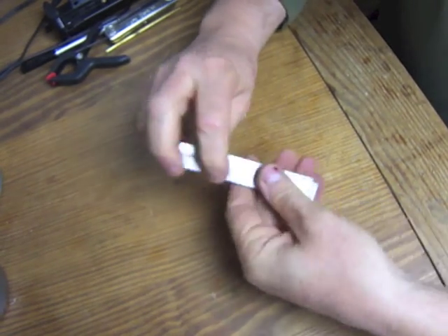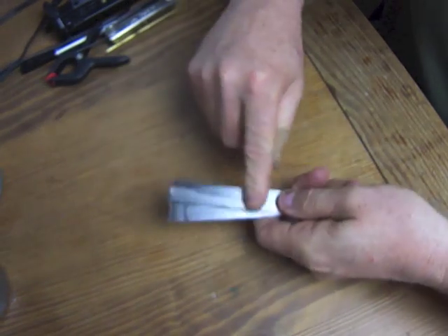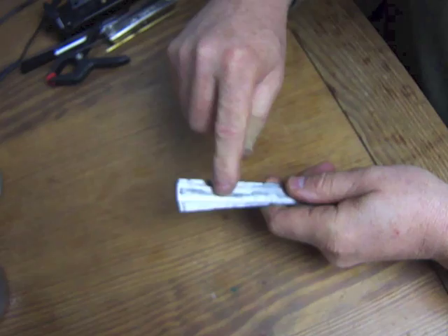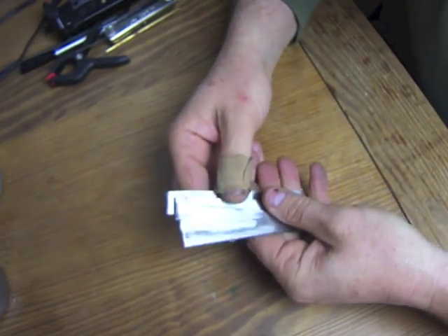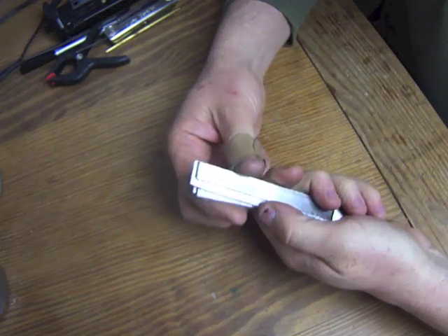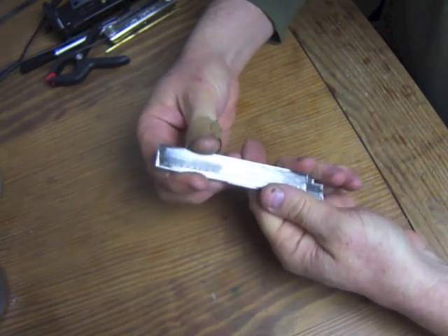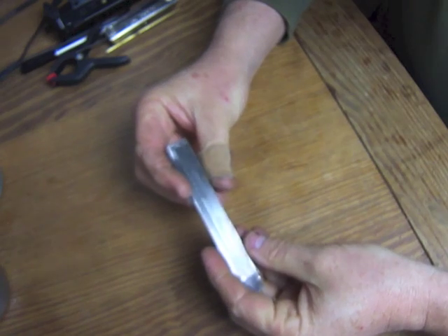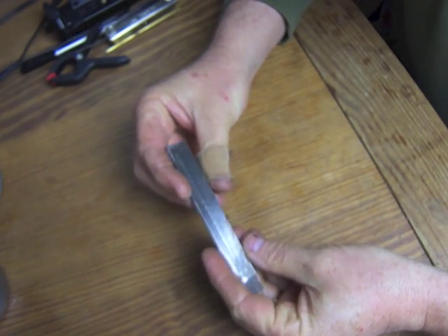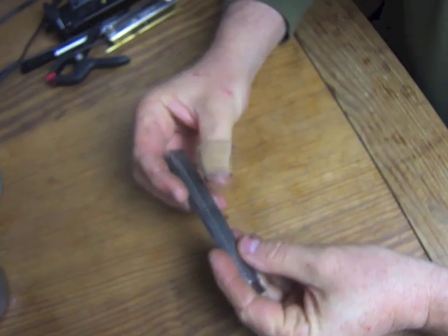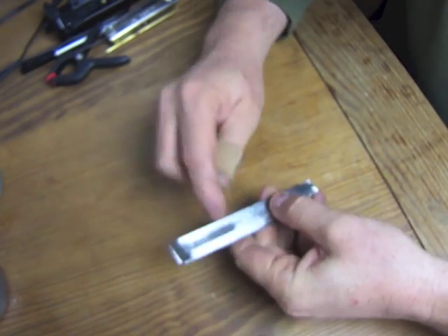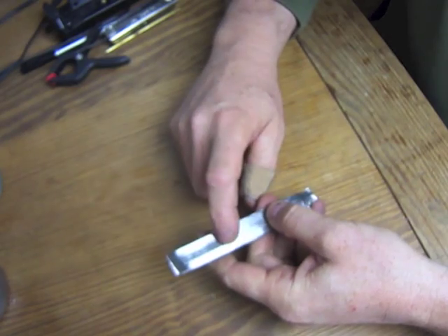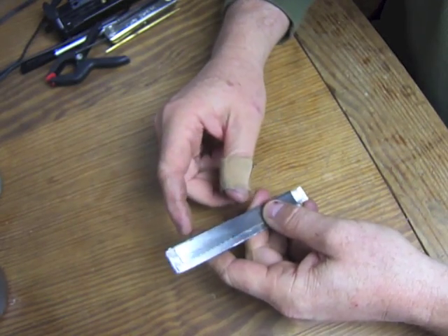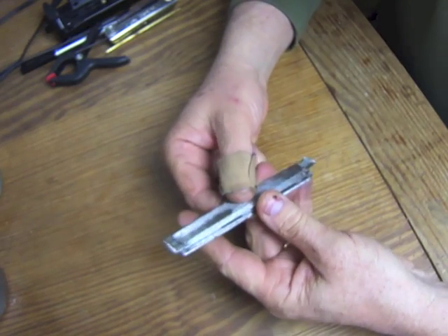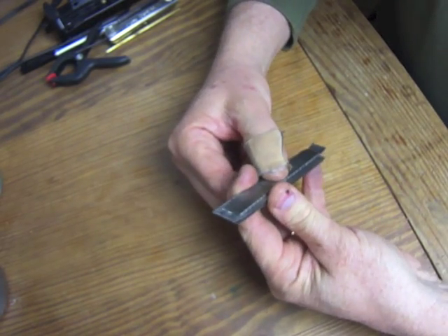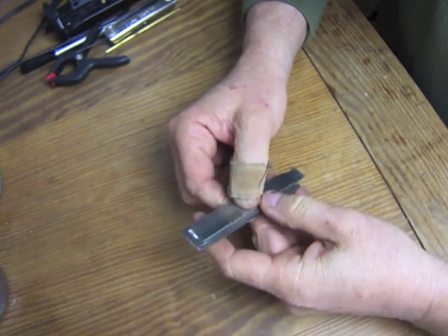So other thing we've done, surface preparation. You can see that with each of these I've run both sides of the metal over my grinder, so there's no scale or rust or anything on there, and that's very important to get a clean weld. The metal always has to be real clean, and that's a problem sometimes with delamination, or you get just a spot somewhere in the steel where you've had an inclusion.